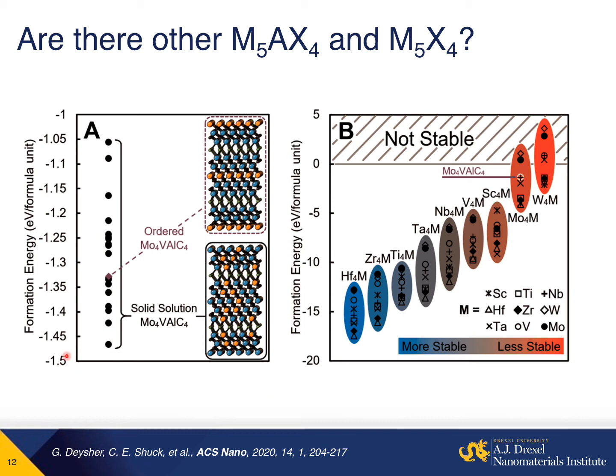Our computational group also investigated the stability of if this is an ordered structure, so if you have the molybdenum and vanadium separated versus having them be random and solid solution oriented. And they found that it seems that the solid solution systems have the lowest energy, so they're the most likely to be possible. So one thing that we need to do is we need to more broadly investigate the chemistry of MAX phases to see if we can produce other phases of the M5X4 structure.